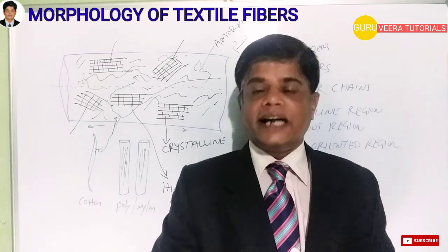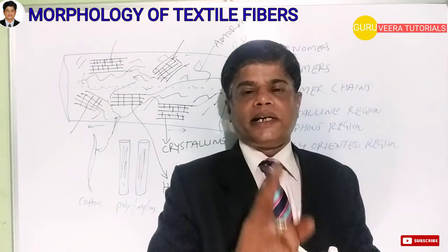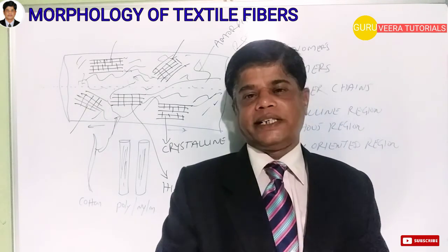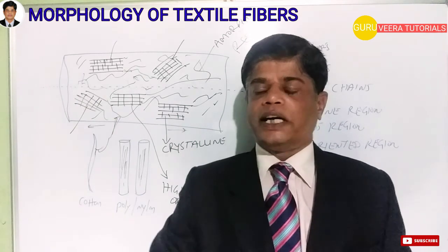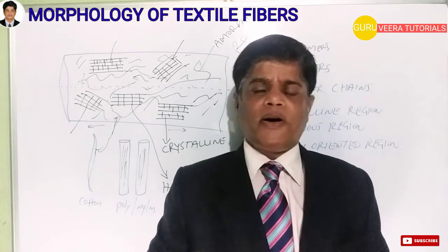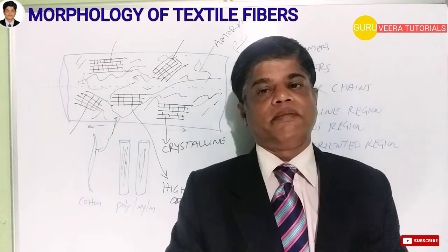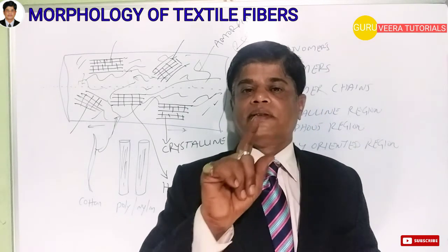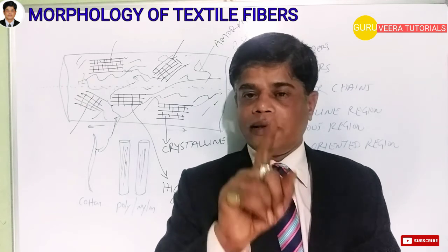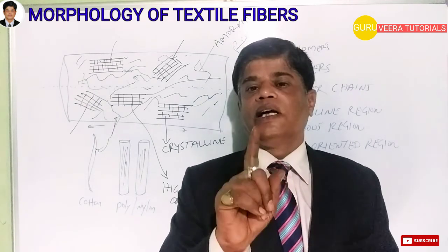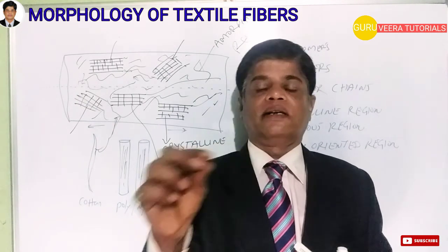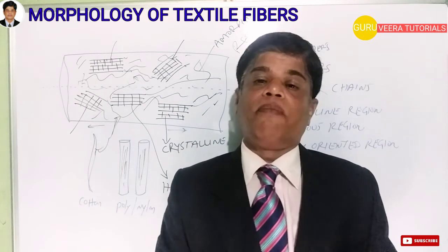To increase the dyeability of the fibers, color modification is not enough; the fiber also has to be mercerized. If natural cotton fiber is not mercerized, the application of reactive dyes may not be efficient. I am not saying 100% efficient, it may or may not be. After mercerization, the pores on the skin of the fibers, the amorphous region, will open. In flattened cotton, the amorphous region is closed. If it is mercerized, the amorphous region will open like a balloon, and there will be space. The reactive dye particles or any dye particles can enter and react with the polymer chains. Right?